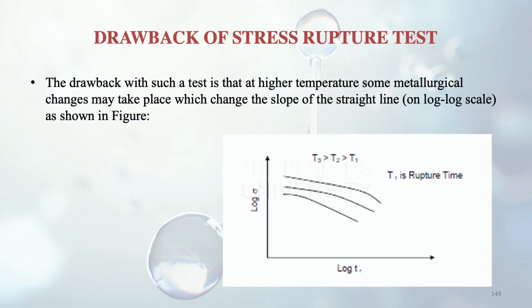But there is a drawback of the stress rupture test. The drawback with such a test is that at higher temperature some metallurgical changes may take place which change the slope of the straight line on the log-log scale, as you can see in the figure. At high temperature the slope is changing.